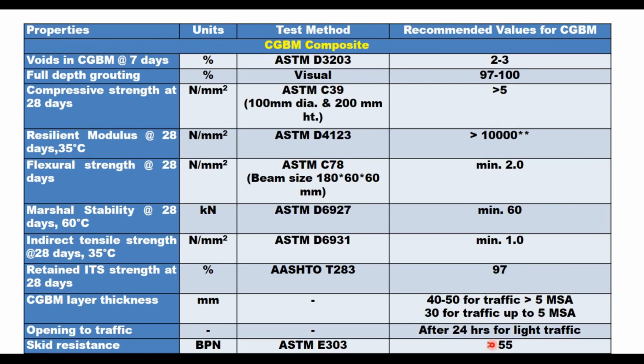The voids in CGBM at 7 days should be around 2 to 3%. Full depth grouting should be achieved up to 97 to 100%. And after the grouting of the specimen, the compressive strength at 28 days should be more than 5 Newton per millimeter square. The resilient modulus at 28 days at 35 degrees centigrade should be more than 10,000 Newton per millimeter square. The flexural strength should be minimum 2, and Marshall stability at 28 days at 60 degrees centigrade should be minimum of 60 kilonewton. The ITS at 35 degrees centigrade after 28 days of curing should be more than 1 Newton per millimeter square, and retained ITS strength at 28 days should be at least 97%.